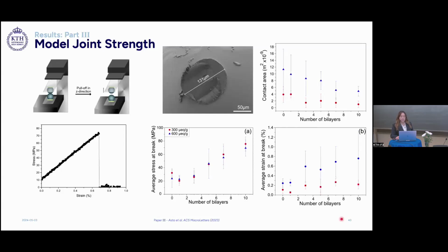Here we can see the strength of the model joints, where both medium charge and high charge beads show similar joint strength. We can see that the contact area decreases when adding the LBLs on the surface, and the highest charged cellulose beads have a larger contact area since they are softer and able to deform more.